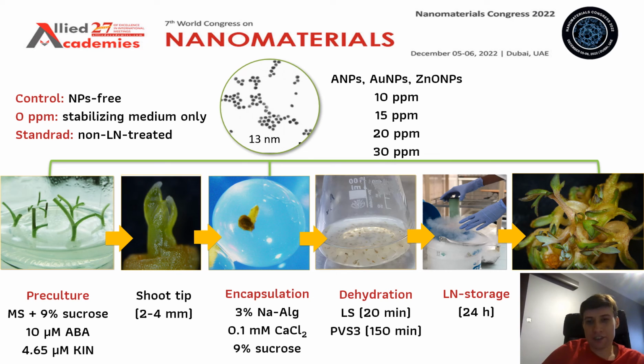On the other hand, the addition of nanoparticles into the recovery medium had a negative impact on the survival and recovery of the plant material, because we observed that the cell membranes of the explants that were inoculated after cryostorage on the medium with an addition of nanoparticles were disrupted. So the cells got damaged. Still, we were able to see that nanoparticles can be useful in cryopreservation if they are added into the alginate capsule.